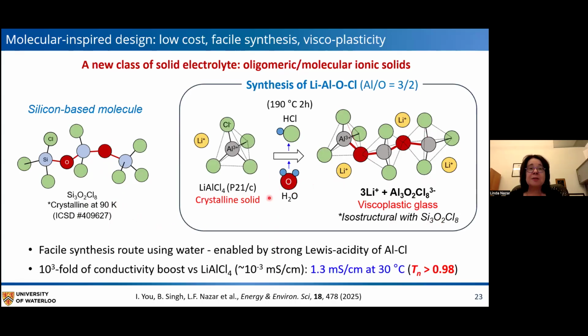And this is done by a fairly simple process, whereupon we carefully hydrolyze the material. This releases hydrochloric acid, and this reaction is carried out at 190 degrees, and the hydrochloric acid is simply pulled out of the system via vacuum. And so it's a very scalable process. As I said, we use a different aluminum to oxygen ratio than the other groups that I mentioned, Yongsheng Hu and Andy Sun, and Kisuk Kang. And whether or not these materials are all similar is kind of an open question.